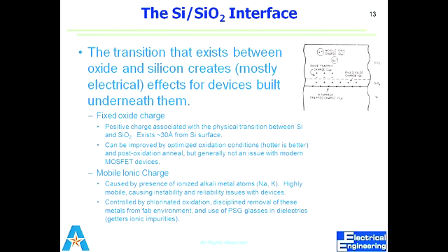Its density, that is, how many of these trap charges there would be, actually depends upon the temperature. The higher the temperature, the lower the density. Means QIT is inversely proportional to the temperature. Secondly, it also depends upon the orientation. Higher the orientation, greater would be QIT.